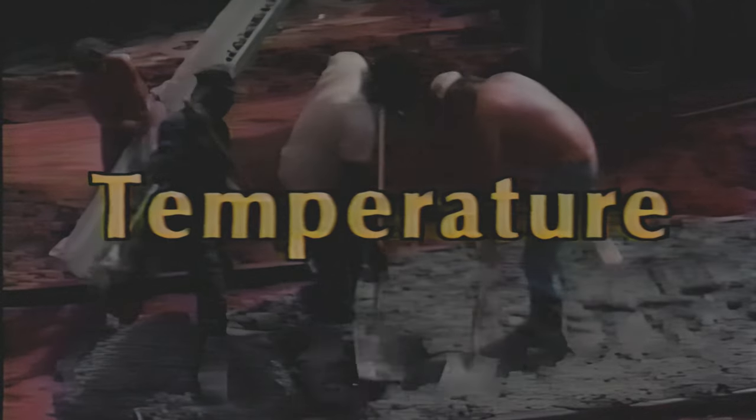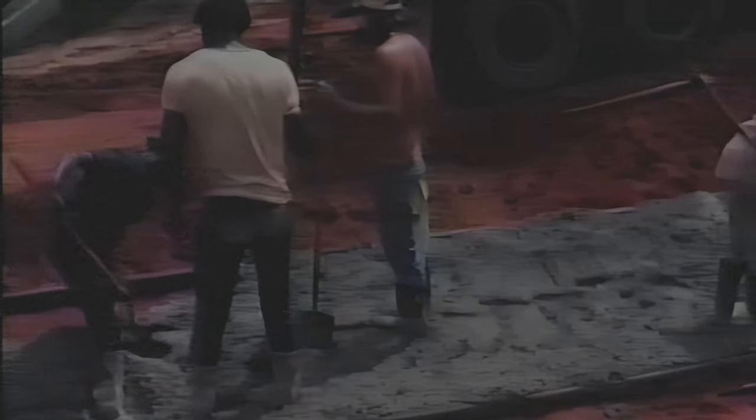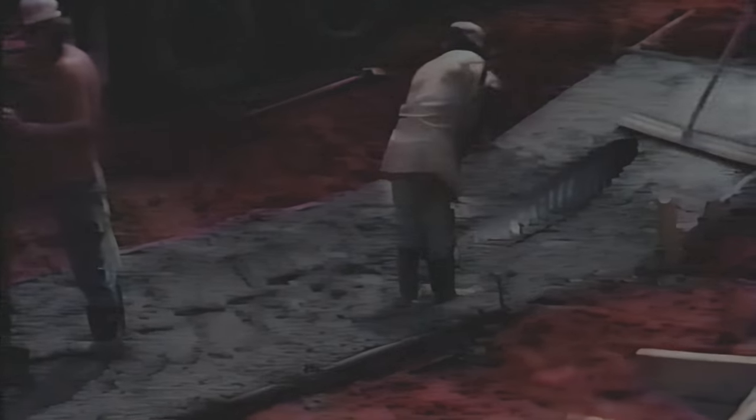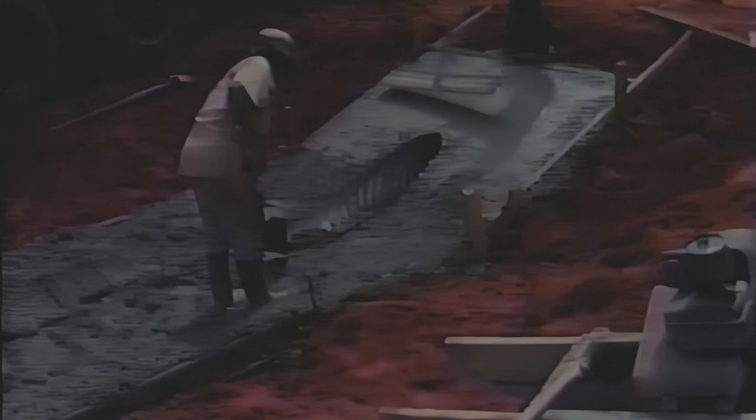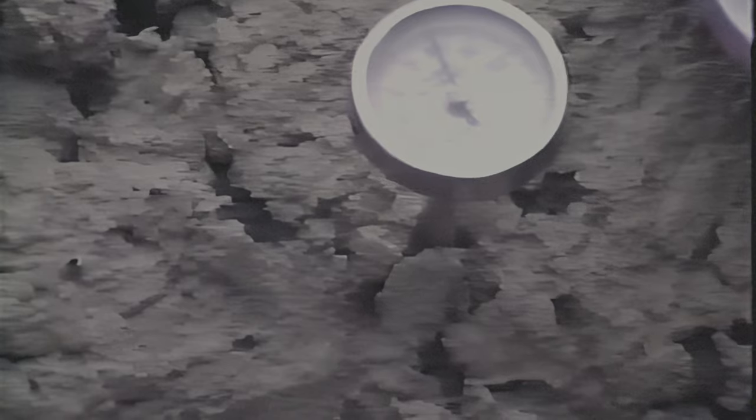Now, temperature. The temperature of fresh concrete affects the rate at which concrete gains strength, the amount of strength the concrete ultimately acquires, and the porosity of the concrete. Checking concrete temperature is simple. It should be done according to ASTM C1064. All that's needed is a standard thermometer, such as an ASTM liquid-in-glass type, or a metal immersion type.